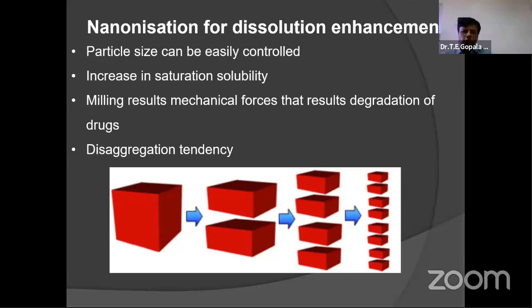Micronized phenacetin showed a high dissolution rate only when subjected to dissolution studies in surfactant medium. The problem is that micronized or nanonized particles have high energy, and because of that high energy, there is a possibility of aggregates or clumps. Thereby, the surface area may not be available during dissolution studies. So we can go for micronization or nanonization, with nano or micron particle size, but later on, on aging, these particles, because of their high residual energy, may convert into different types of aggregates. Thereby dissolution may not be as required.